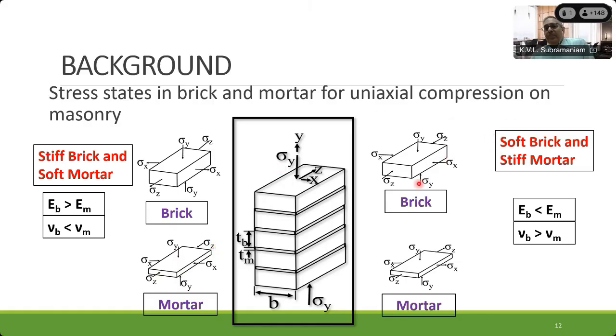Whereas if you come to the case of the soft brick, the story completely reverses. Now the modulus of the brick is smaller than the modulus of the mortar, but the Poisson's ratio of the brick is much larger than the Poisson's ratio of the mortar. So when we apply a compressive stress on the brick and the same compressive stress acts on the mortar, the mortar wants to expand less than the expansion of the brick. So what happens is that the brick goes into a state of triaxial compression and the mortar into biaxial tension with uniaxial compression in the vertical direction. So the dangerous state of stress is basically this biaxial tension. So basically the mortar is now in tension. And I'll show you how this plays out in the failure of the brick.